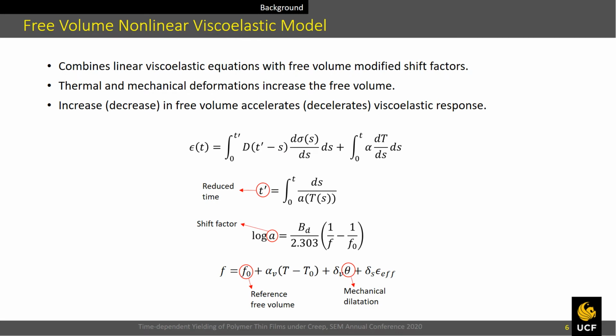The viscoelastic response of the SF420 has been studied extensively before, and previously a non-linear viscoelastic model based on the free volume was developed. I would like to give a brief background on the free volume non-linear viscoelastic model, which is also used in this study. It can be considered as an extension of linear viscoelastic equations, but the shift factors are dependent on free volume. The thermal and mechanical deformation increase the free volume, and increase in the free volume accelerates the viscoelastic response.